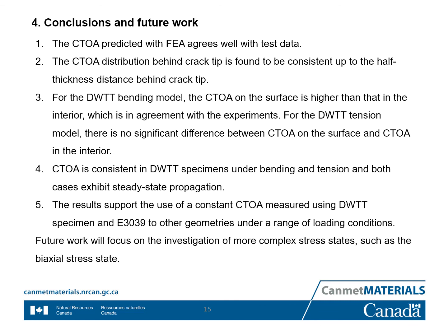Fourth, the CTOA is consistent in both bending and tension model, and both cases show a steady state propagation. Finally, the results from this research support the use of a constant CTOA measured using drop weight tear test specimen and ASTM standard E3039 to other geometries under a range of loading conditions.